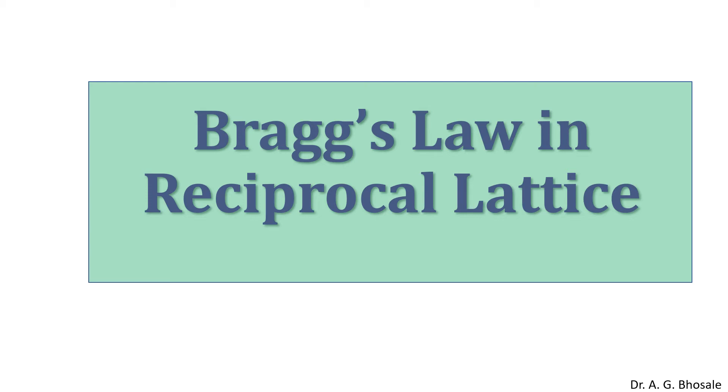Today we continue with Bragg's law in reciprocal lattice. In an earlier lecture, we discussed Bragg's relation using X-ray diffraction by crystal planes, and obtained the condition 2d sin θ = nλ. Its geometrical representation was also shown earlier, where sin θ equals (1/d_hkl) divided by (2/λ).